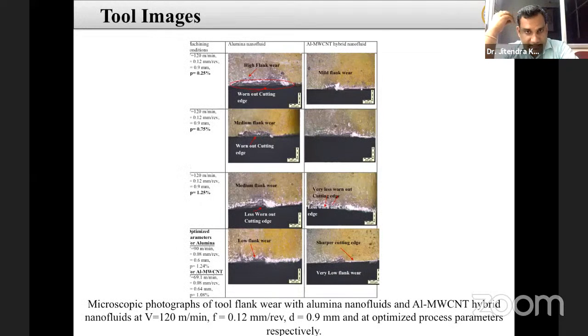And these are the tool images which I have taken from the microscope, and you can see that this is the alumina one, and this is the nano hybrid one. And in this hybrid one, very low flank wear is obtained. Whatever optimized parameters we got from the software RSM method, we have also tested, and we can see clearly that at the optimum there is very low flank wear on the cutting edge, very small wear happened rather than the other cases.